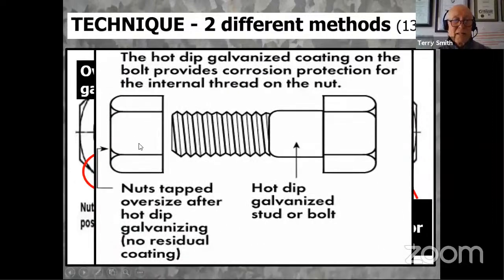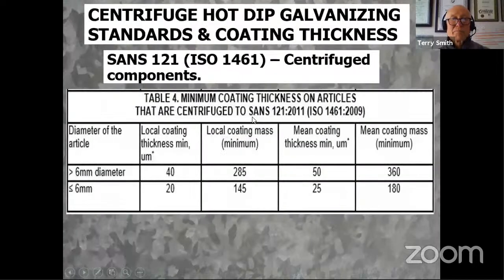So you can see the nuts are galvanized as blanks, and after galvanizing, they're tapped oversized to accommodate that extra coating thickness that you have on the bolt. And how that works is remember the cathodic protection that both Simon and Martin have talked about. There's no coating on the inside of the nut, but once you turn the nut up to its tension, there's ample zinc surrounding that area to give you cathodic protection.